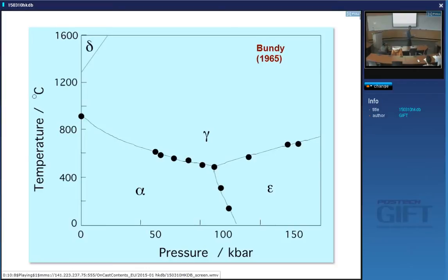So by putting pure iron inside a copper matrix, you force it to remain austenitic, and then we can pick up that it's antiferromagnetic below 80 Kelvin. Okay? I can attract austenite with a magnet. In other words, ferromagnetism. The way I would do it is I would add quite a lot of nickel to the material, and that retains the ferromagnetic state of austenite. So austenite is not always indifferent to the presence of a magnet. It can be ferromagnetic, it can be antiferromagnetic.